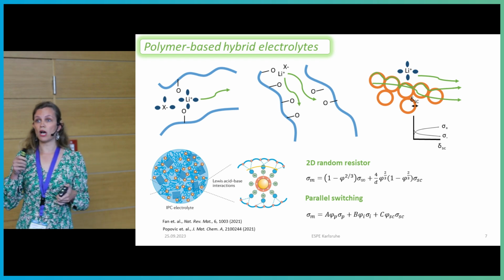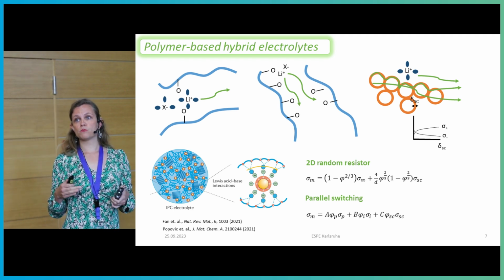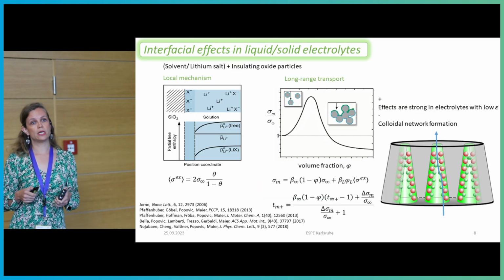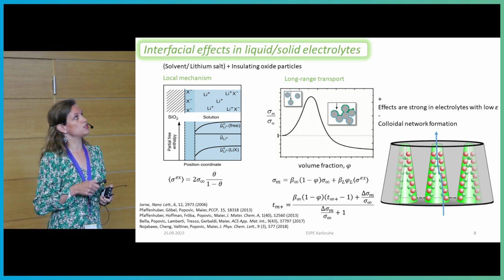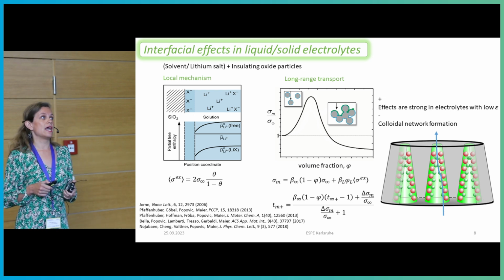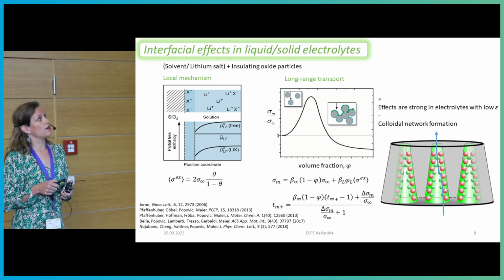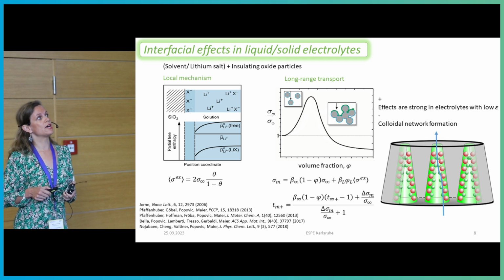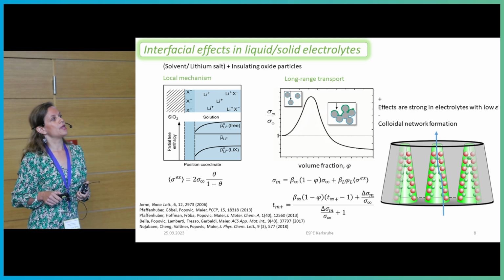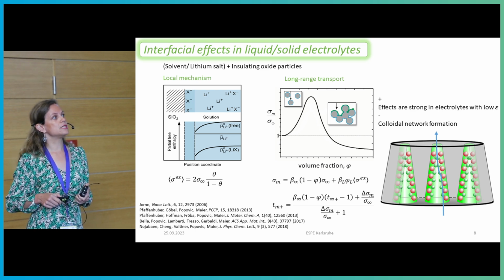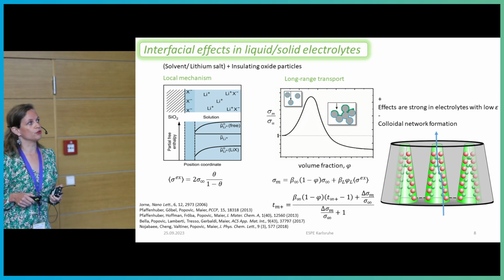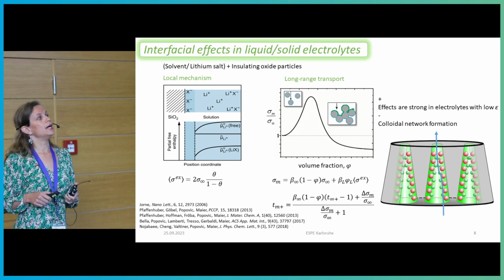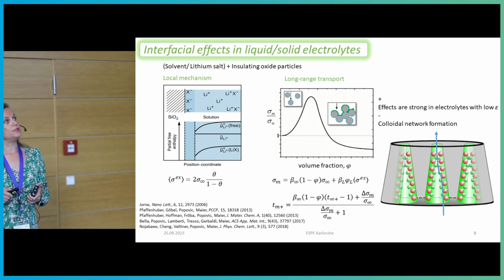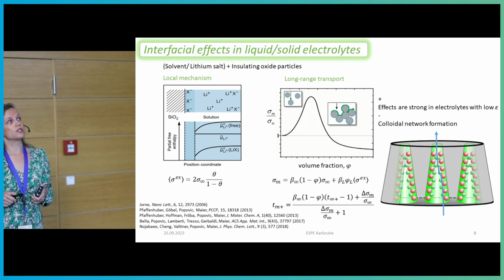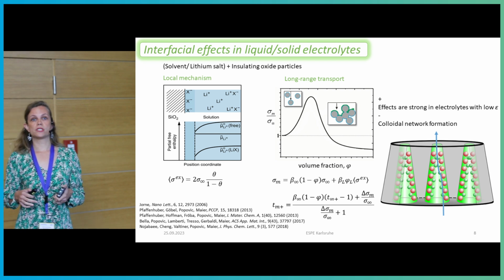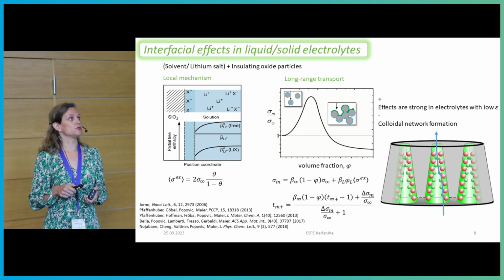So it's not always easy to access those parameters, but in one of the systems that is kind of the simplified version of it, which is the liquid-solid electrolytes, in which we have space charge zone formation at the interface, this can be sometimes possible. So in these electrolytes, we have an interfacial effect, but in order to have long-range transport, we need overlapping space charge zones. And then we can kind of describe this in this parallel switching model in terms of either ionic conductivity or the lithium transference number. And the interesting point here is that these effects, the interfacial effects, are strong in electrolytes with low dielectric constant, but we might have, of course, from the colloidal perspective, a massive problem in terms of colloidal network formation.